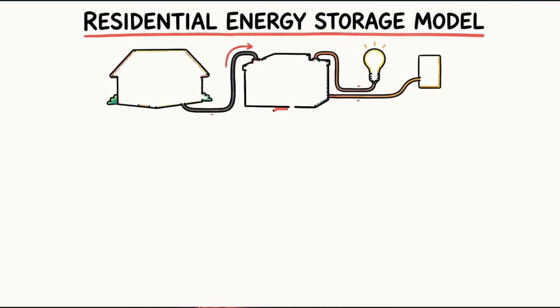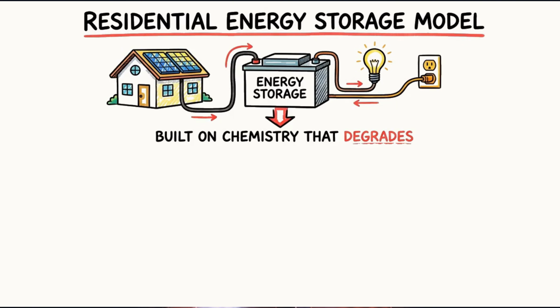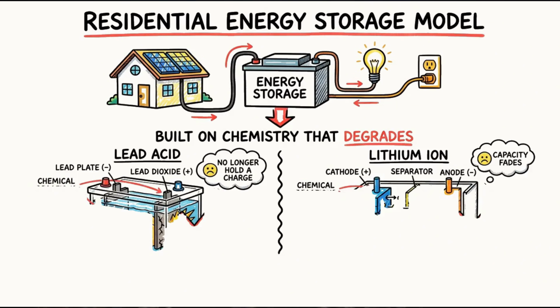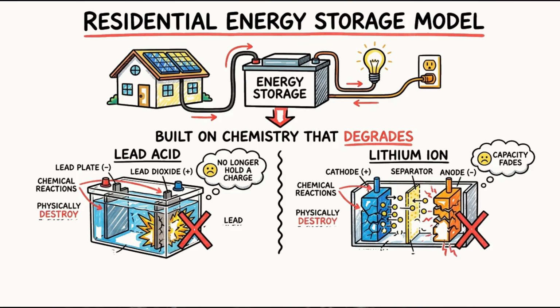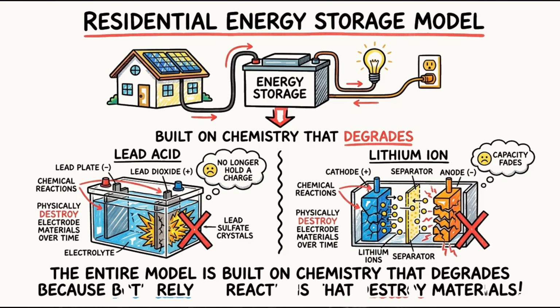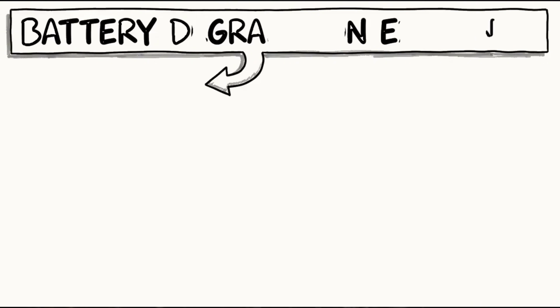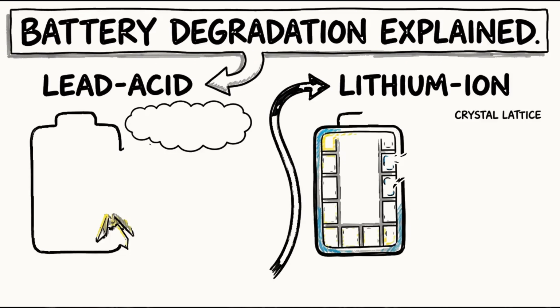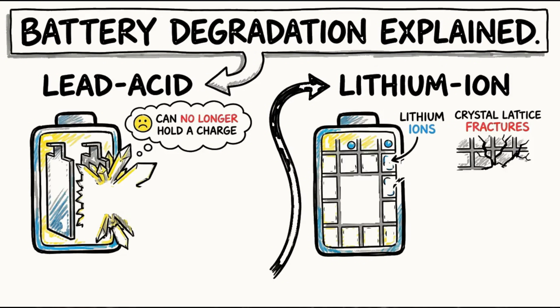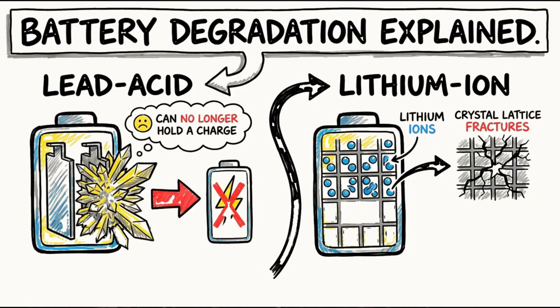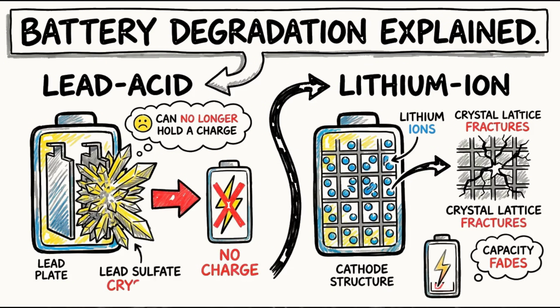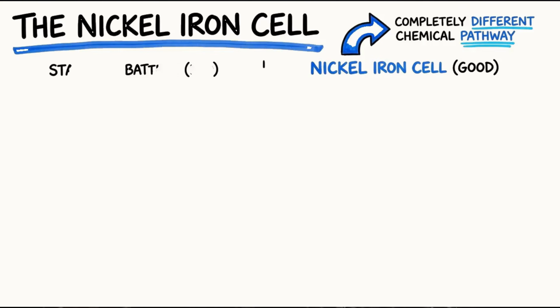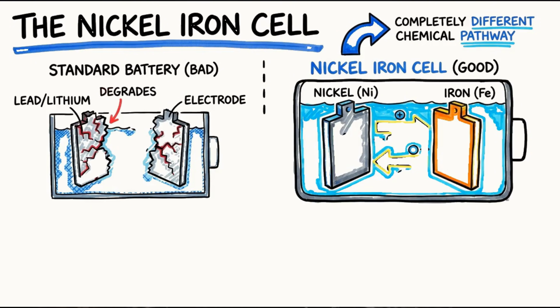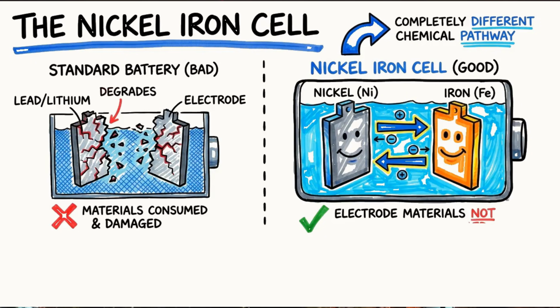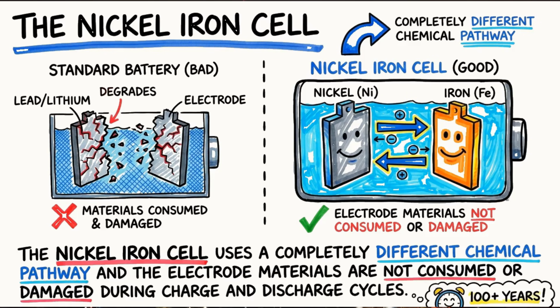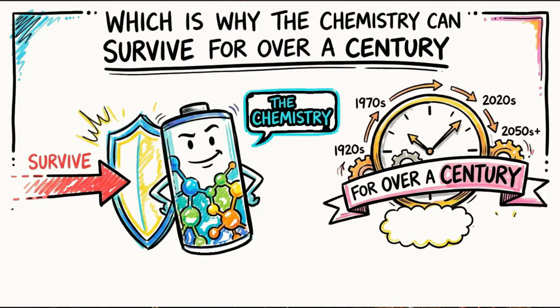The entire residential energy storage model is built on chemistry that degrades, because both lead-acid and lithium-ion batteries rely on chemical reactions that physically destroy the electrode materials over time. Lead sulfate crystals grow on lead plates until they can no longer hold a charge, and lithium ions embed themselves in the cathode structure until the crystal lattice fractures and capacity fades. The nickel-iron cell uses a completely different chemical pathway, and the electrode materials are not consumed or damaged during charge and discharge cycles, which is why the chemistry can survive for over a century.